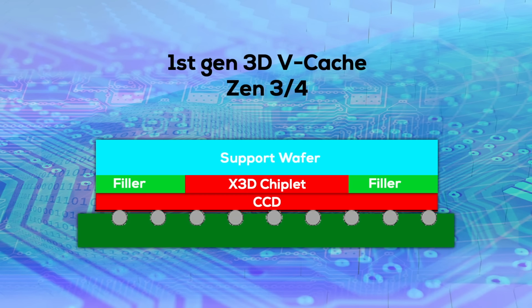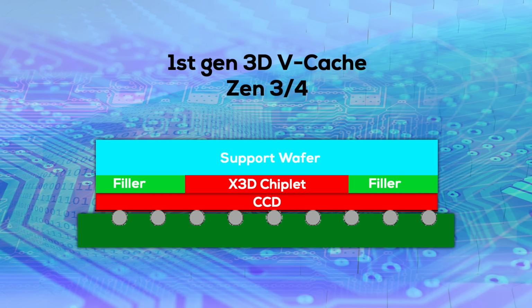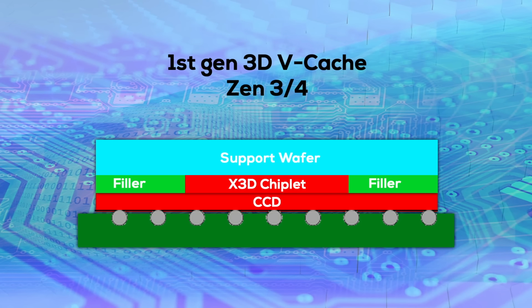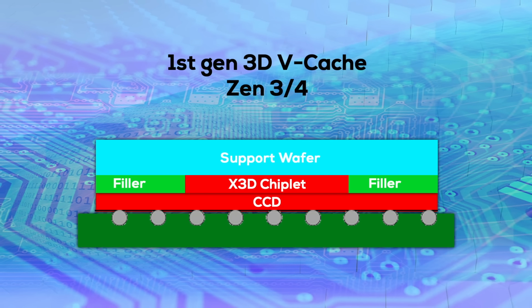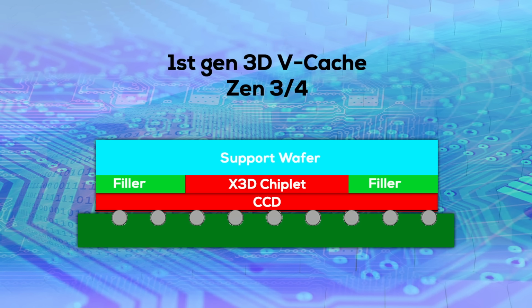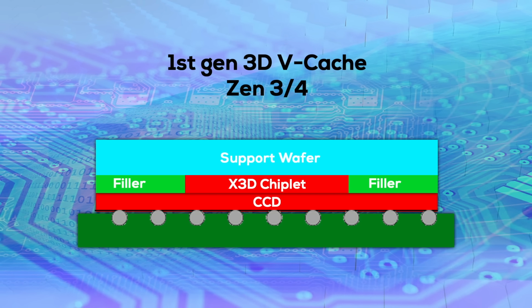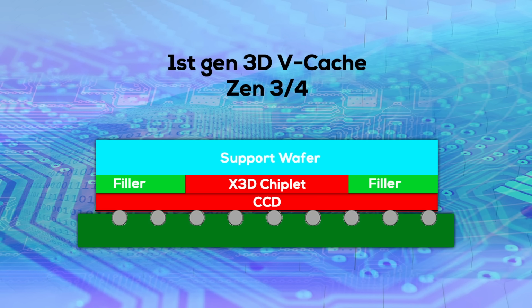The thinned Zen 4 CCD is on the very bottom. Right above is the thinned cache chiplet and the two filler pieces that even out the surface area during hybrid bonding. And above that, we have the actual structural silicon that gives structural support to the whole stack and allows it to reach the same height as a standard Zen 4 CCD. That's how a first-gen 3D V-cache CPU really looks like. It's a silicon sandwich with 5 different pieces, 3 of which are filler and support silicon, only 2 are active.